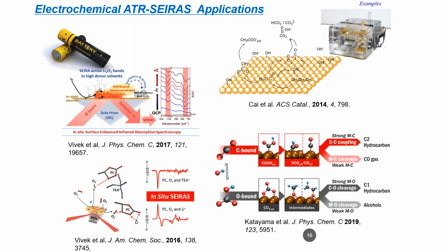So also, when you apply a thin electrochemical layer on the top of the electrodes, depending on the thickness and also on what kind of metal layer you use, you can create enhancement of the signal. This enhancement is called ATR surface-enhanced infrared absorption spectroscopy. The enhancement of the signal tremendously helps to see what's going on exactly on the surface of the electrodes. So that technique is very well developed. The key point is to make a very good coating layer, a metal layer, on the FTIR electrodes. All this technique is described in the publications shown here. And thank you, Jan Burgess, for providing me this slide.